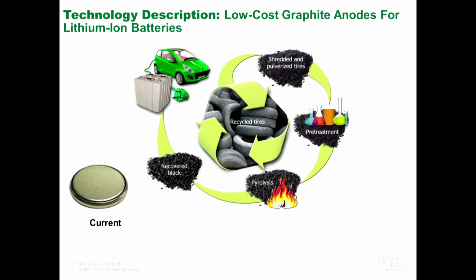And what we have developed is we have introduced an acid treatment method, mainly the sulphonated method. So you just take the shredded powders, go through the acid treatment and pyrolyze it. It's like a two-step process. You shred it, go through the acid treatment and pyrolyze it, and recover the carbon black. So what we call is sulphonated tire rubber derived carbon.